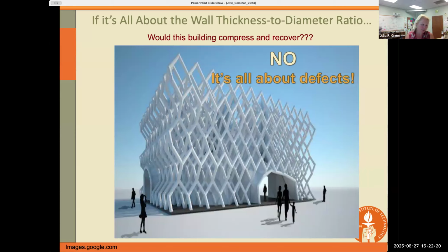So we all know brittle materials fail at flaws, and the probability of finding a flaw, maybe thousands of flaws, hundreds of thousands of flaws in something that's this large is 100%, whereas in something that's only nanometer sized, first of all, the size of the largest flaw is only 10 nanometers or whatever that thickness is. And then the probability of finding a flaw is much, much lower. So what this is teaching us is that if we were to fill up the same volume, like a room, for example, with a nano-architected material versus just a regular fully dense material, we're going to get much better material properties in the nano-architected world.